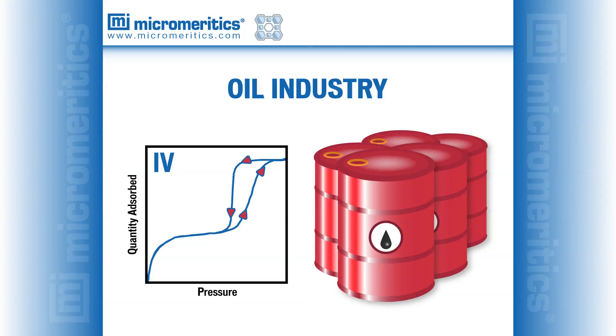The texture of the catalyst plays a very important role in its activity and selectivity. The optimum texture, of course, depends on the kind of reaction that is to be performed. For example, mesoporous catalysts with pores approximately 10 to 15 nanometers in width are used in different hydro-treating processes.